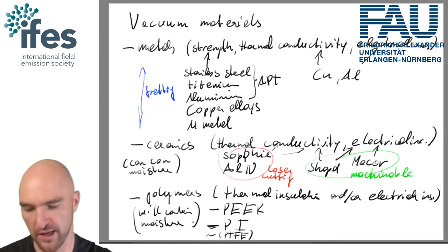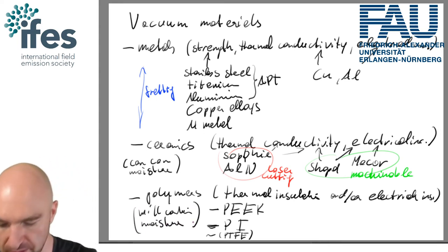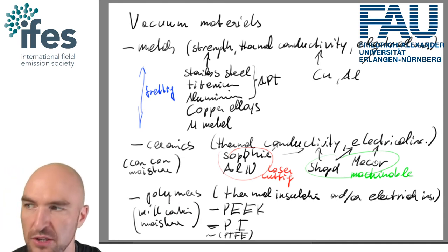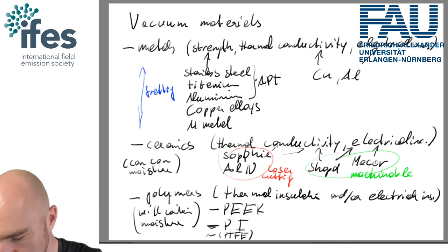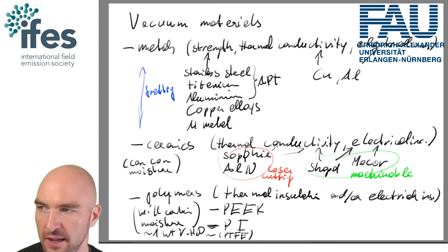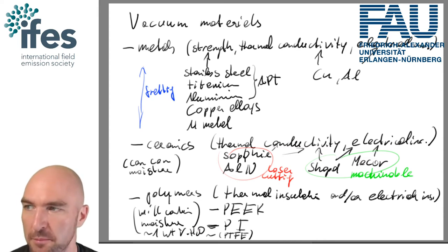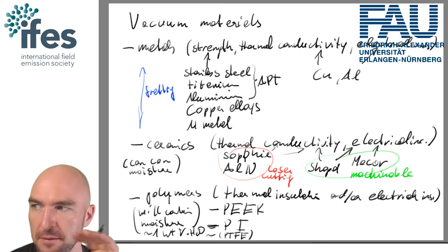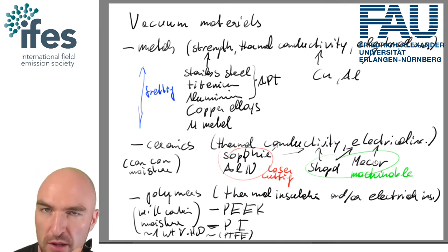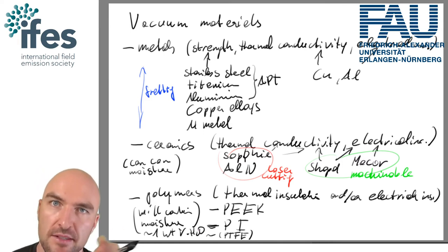So in terms of ultimate vacuum performance, polymers are actually not that bad. The problem with them is they will take up around 1 weight percent water vapor at room temperature. So they're hygroscopic, so at ambient pressure, if you leave it out before you put it in, it will pick up about 1% of water vapor. It can move relatively quickly between the polymer chains and will then outgas during your bakeout and during your subsequent